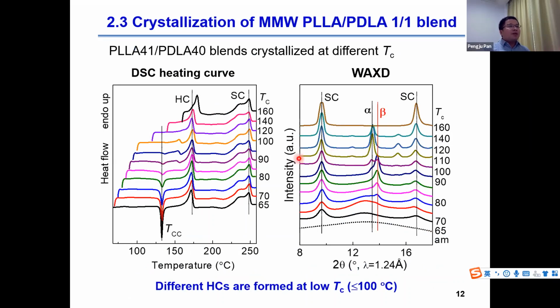To further confirm the unique crystalline structure of the medium molecular weight blend, we crystallize the sample over a wide temperature range from 60 to 140 degrees C, study the heating process by DSC, and measure the crystal structure by XRD. For the blend crystallized at a temperature lower than 100 degrees C, we see an additional crystallization peak in the heating process. This suggests the crystallization is constrained in the isothermal crystallization process. For the sample crystallized at a low crystallization temperature, the diffraction peak shifted to a higher angle compared to the common homocrystal. This means the medium molecular weight blend forms a unique homocrystal under this condition.